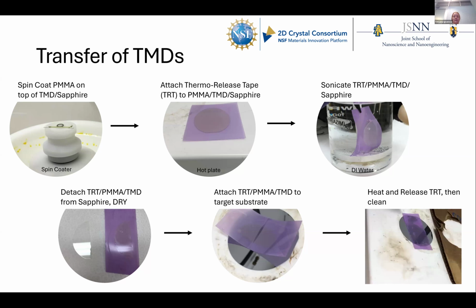I spin coated PMMA, let it dry, and then I put it on the hot plate and attached a thermal release tape on top. Once you put that system in DI water and sonicate for 5 minutes, it's easy to peel the thermal release tape from the sapphire, and the tape has both the PMMA and TMD attached. Then you can attach that to a target substrate, in this case silicon. Once you heat it up, the bonds between the TMDs and the silicon attach, and you get a nice, beautiful layer of TMDs.